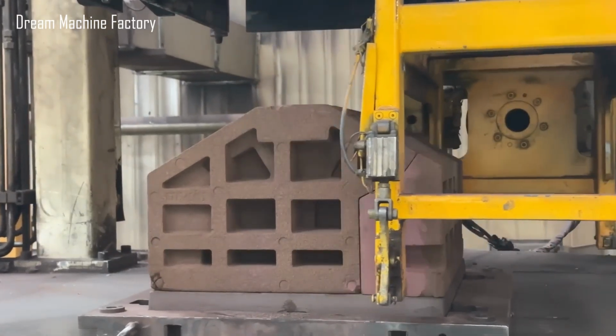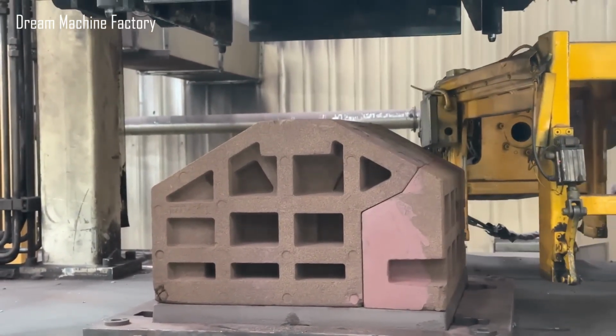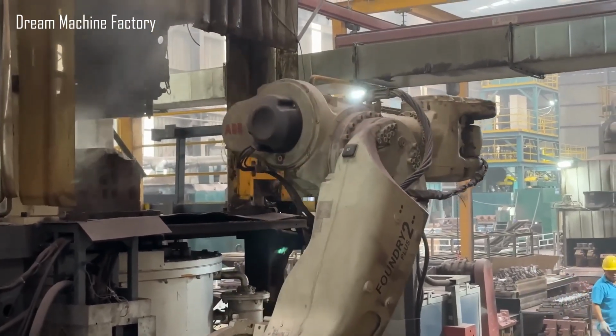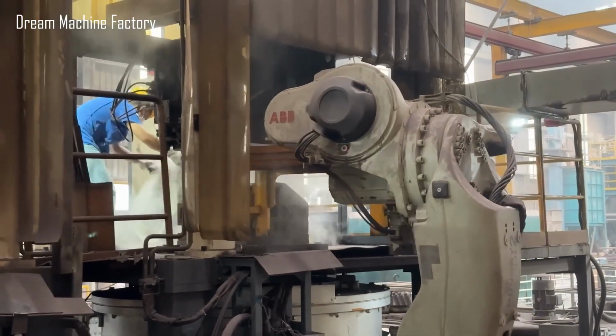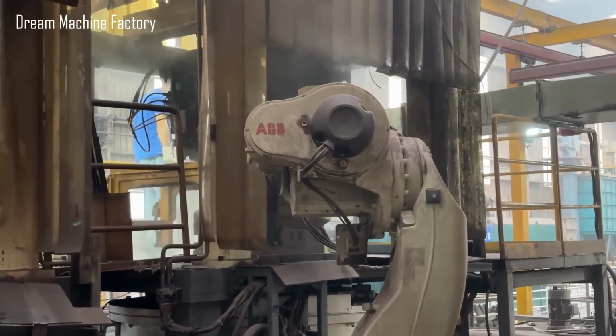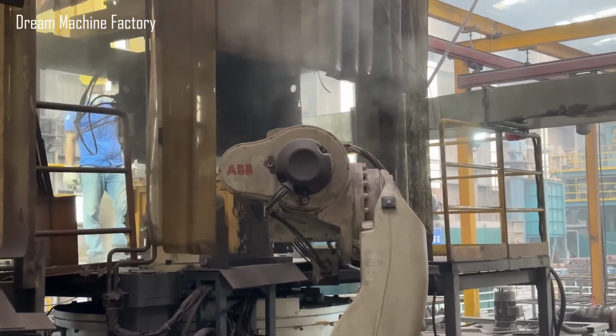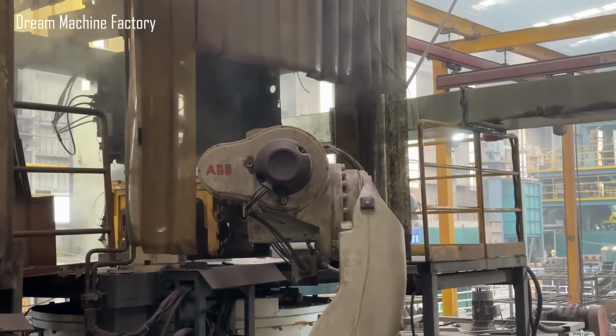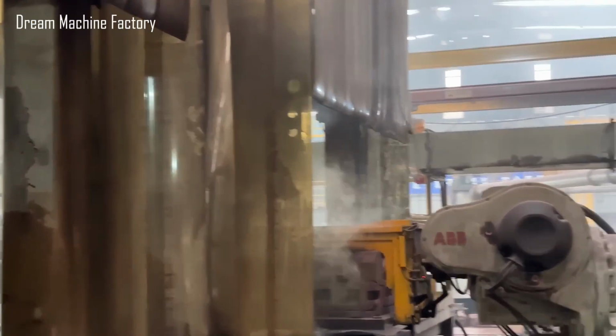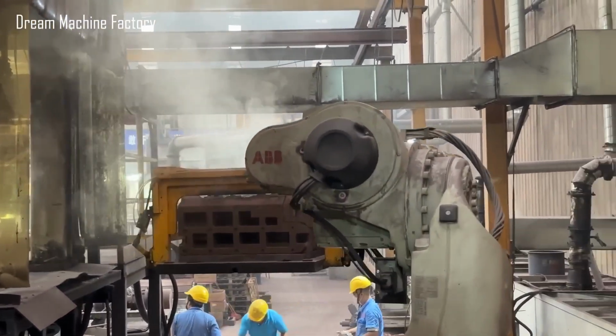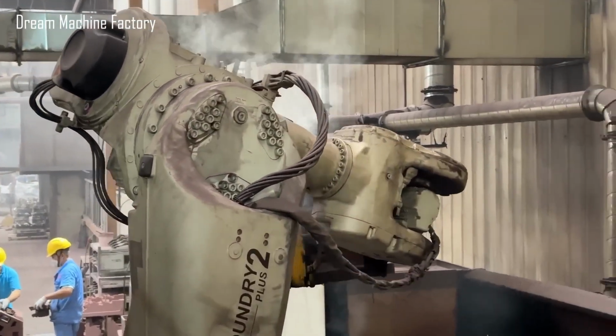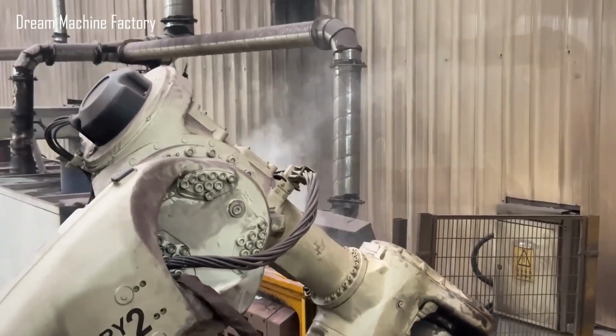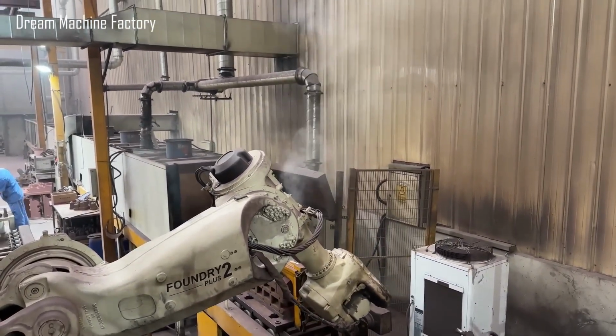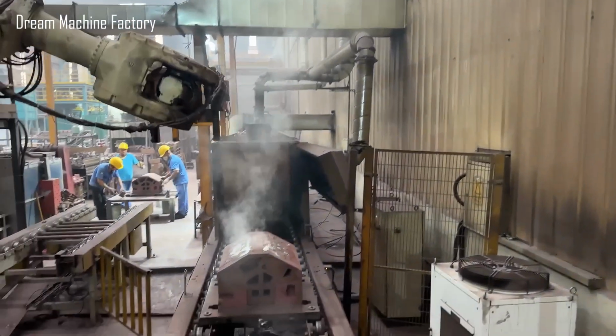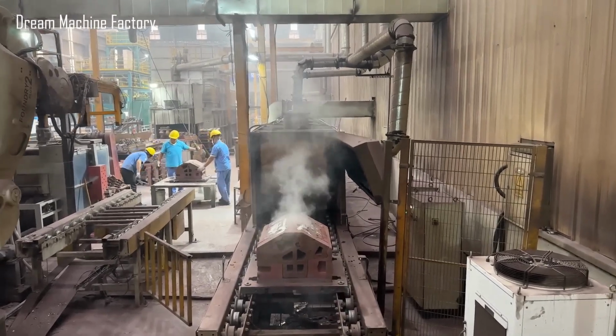Low-pressure casting is a precision method used to produce high-quality V6 engine blocks. In this process, molten aluminum, or other metals, is contained in a sealed furnace below the mold. A low-pressure air supply, typically 0.5 to 1 bar, is applied to gently push the molten metal upward through a riser tube into the mold cavity. This bottom-up filling minimizes turbulence, reducing the risk of gas entrapment and oxide formation. The controlled flow results in a dense, uniform casting with fewer defects and improved mechanical properties. The process allows for excellent dimensional accuracy and repeatability, especially important for complex engine blocks. After solidification, the pressure is released, the casting cools, and the mold is removed for core shakeout and further processing.